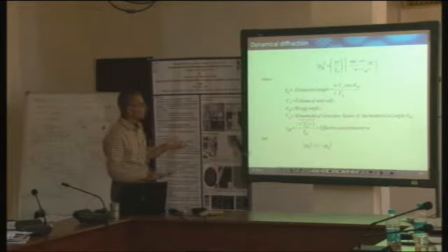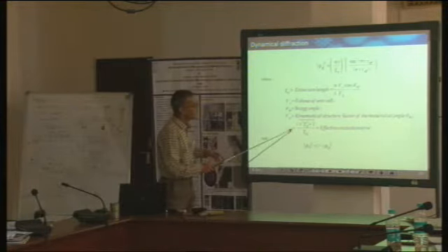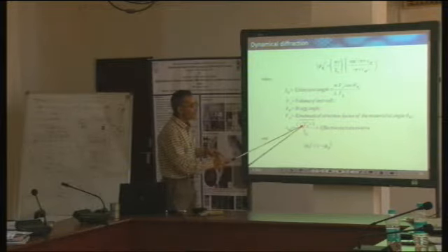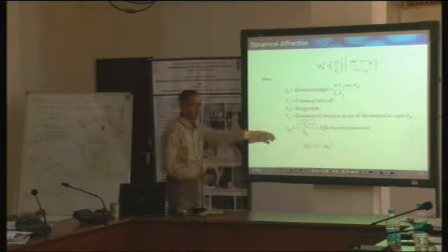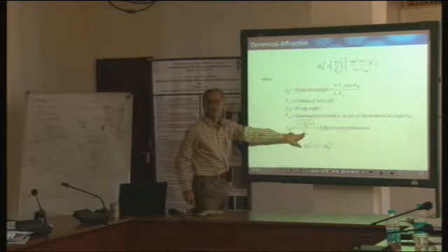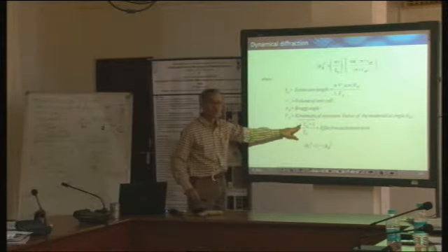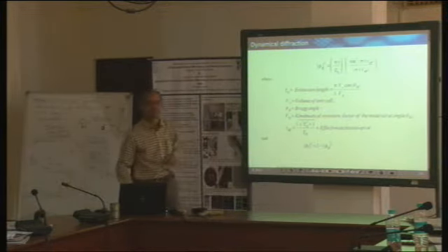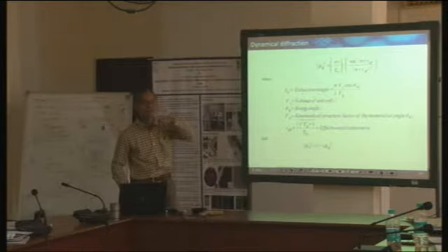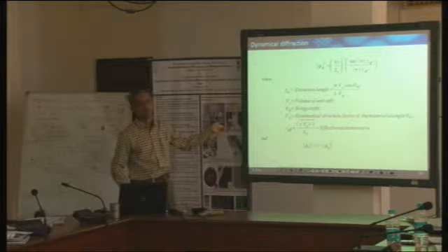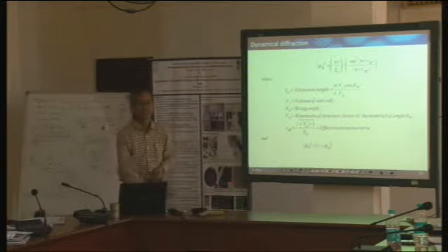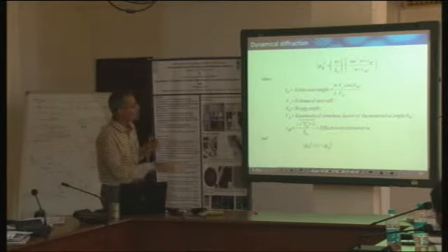Now, are we entitled to take that limit? Not anymore, because here S effective is equal to the square root of S squared plus 1, divided by xi g. So now even if you make S equal to 0, S effective doesn't become 0. So that limit tending to 0, which was causing us problems, doesn't happen anymore. It is this way that this helps to take care of things.